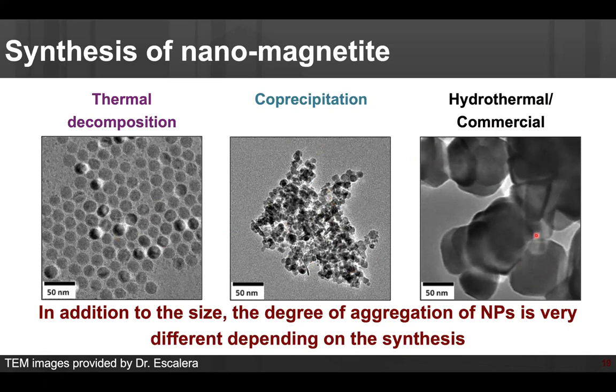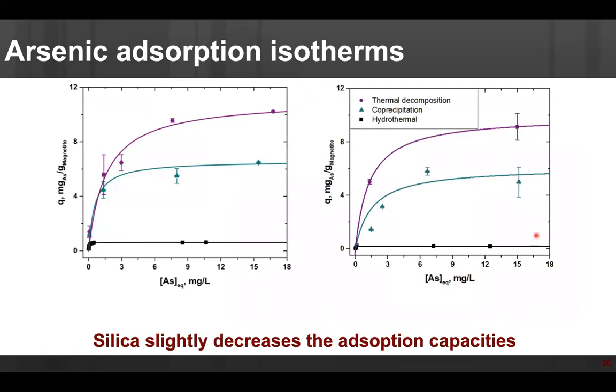So the first thing I want to do is arsenic absorption isotherms, and we can see that the nice materials have the better performance. We have a big isotherm here, followed by co-precipitation and then hydrothermal. We do the same with silica present, and we can see that, yes, in these conditions, we have a slight decrease in absorption capacities, but it shouldn't be as big, right? The main factor that we have to worry about is agglomeration.